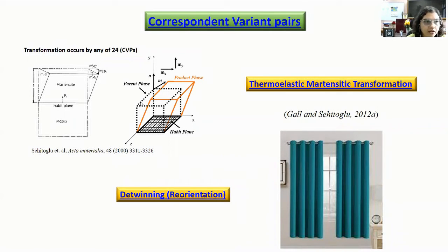If one crystal pattern changes to another one, there has to be a common basis. That common basis is what is called the habit plane. And what will be the structure of this habit plane? The entire details are very well encoded in the phenomenological theory of martensitic transformation. This is theoretically very well developed, and people have tried on several occasions to show it experimentally also. With respect to the habit plane only, you can find the change of shape. Is it mandatory that one plane should be habit? Yes, there should always be one habit plane.